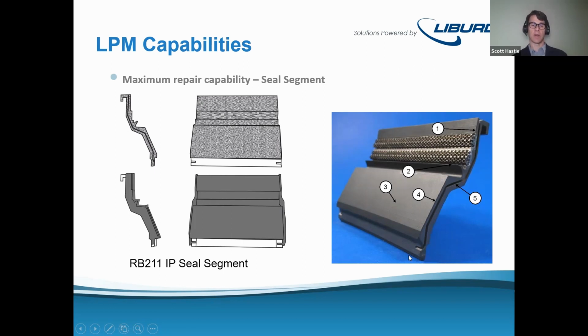And what that allows our overhaul shop that we support on these repairs to do is that they can put a brand new part against a repair part, and they slot together like two brand new parts, because they're all machined. These seal slots are machined with respect to their as-new datums, and they slot together quite nicely. And this is really important if your repair yield isn't 100% and you've got whatever, 32 repaired parts, and you're trying to put two brand new parts in there, you're going to run into trouble unless you do this full repair.